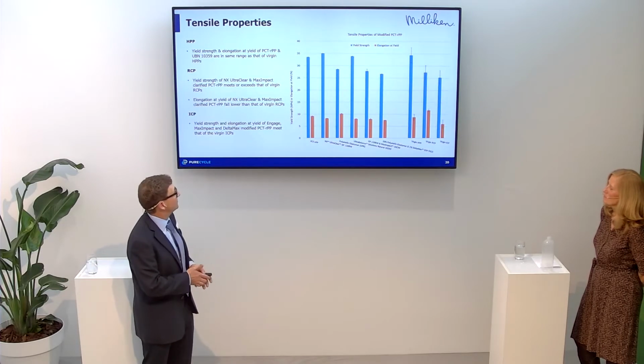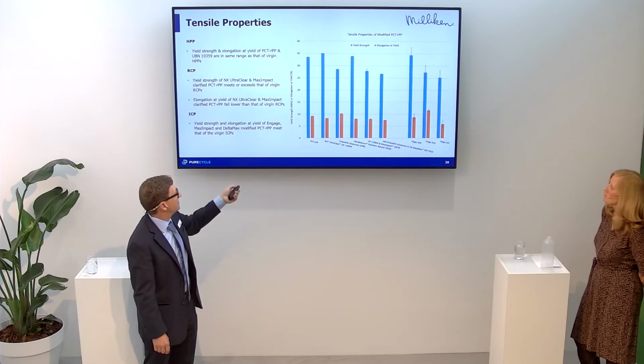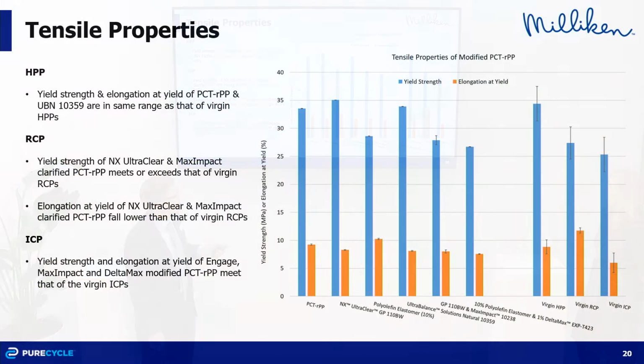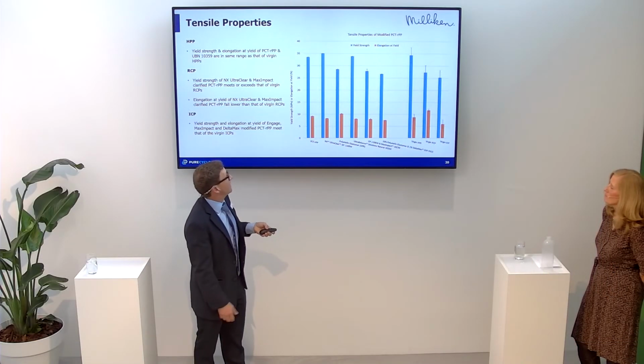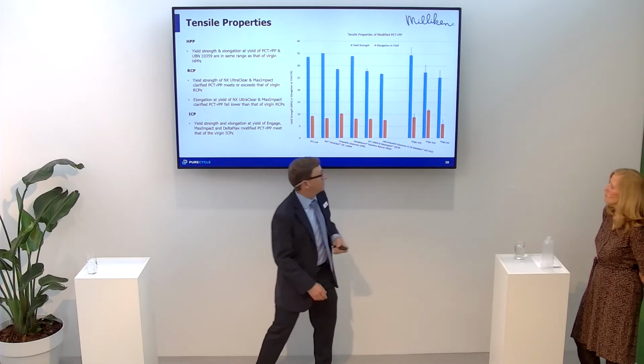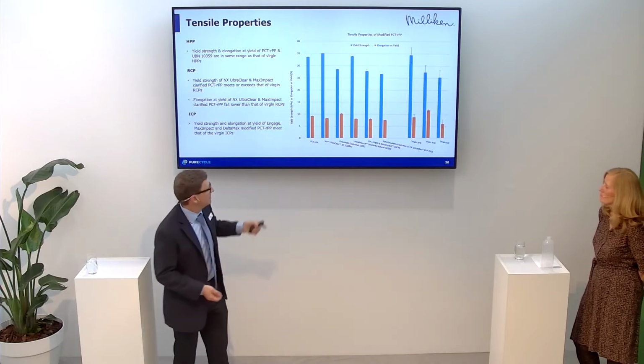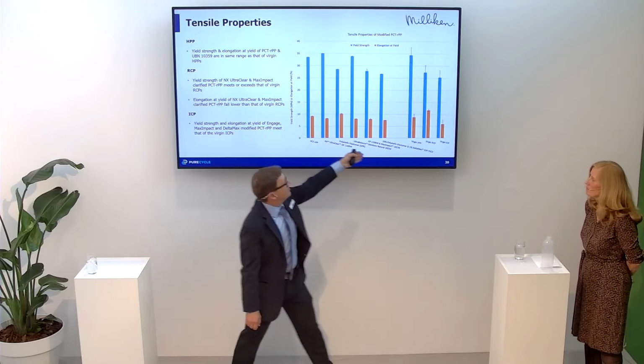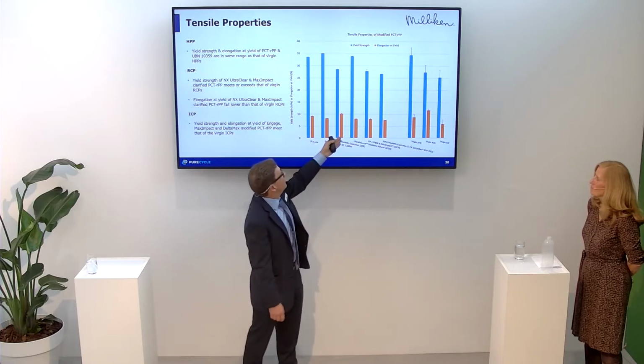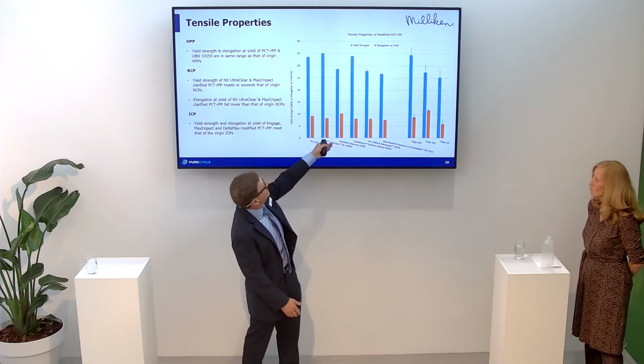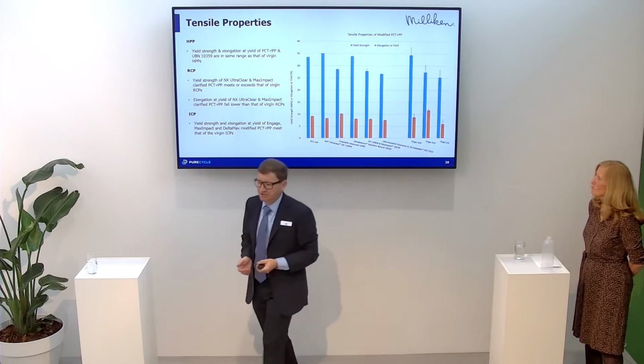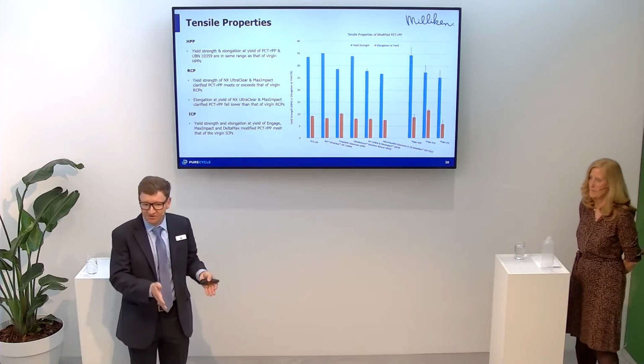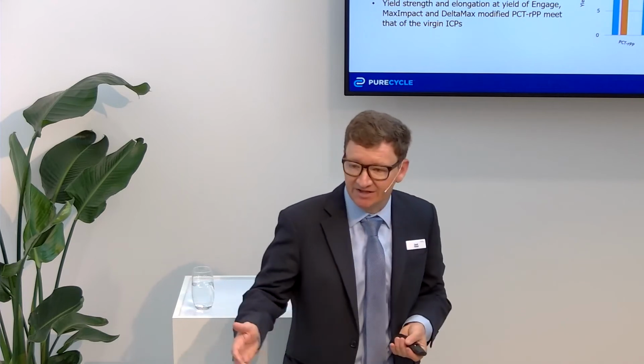In terms of tensile strength, I have yield strength and elongation at yield plotted. Yield is in blue, elongation at yield is in orange. And just the starting material, again, yield strength is about 33 megapascals, which matches very well to a virgin RCP or virgin homopolymer. The clarified one, a little higher at 35, higher than the RCP. The impact modified at 30, 28 or so, in the same range as a virgin impact copolymer. So taking this one stream from PureCycle and adding the different Milliken additives, we really feel that we could tailor a solution to your individual needs to match what you're currently using in terms of virgin production.